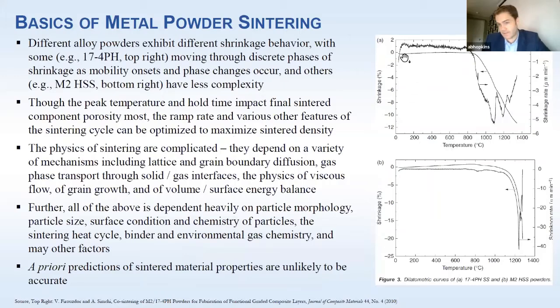As you can see, the 17-4 PH, as temperature reaches a certain range, you start to shrink rapidly. You saw that on the previous slide. This is a phase change going on. Then you stop for a bit, you shrink less rapidly, and then you reach a delta ferrite phase. So you have another phase that becomes stable, delta ferrite phase 17-4, and then you shrink rapidly again. And then you've shrunk about all you can, you stop shrinking as rapidly, and you reach an equilibrium where the pores are gone.